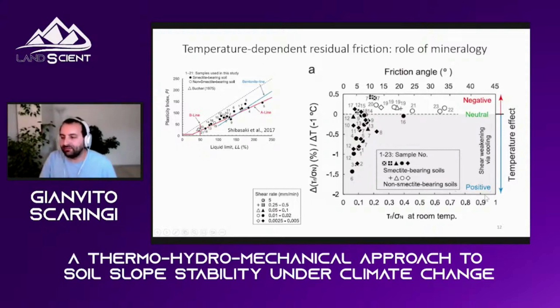They call positive an effect that is consistent in sign: high temperature, high strength; low temperature, low strength. They call negative an effect that is reversed, inconsistent with that, meaning strengthening upon cooling, weakening upon heating. And they noticed that the more smectite, the lower the friction angle the material had, the stronger was this cooling-induced weakening. And the magnitude of these effects is very similar to the magnitude of thermal pressurization, actually, 1.5% per degree, suggesting that probably the phenomenon has the same physico-chemical root.